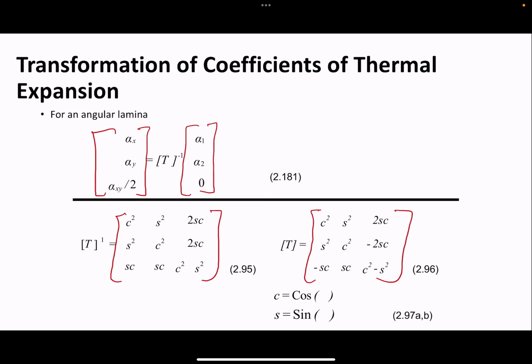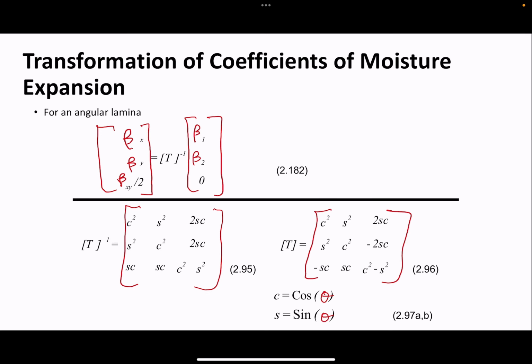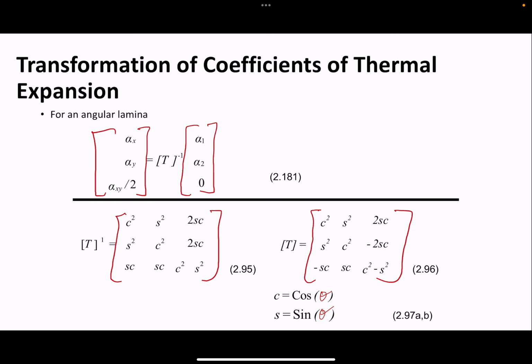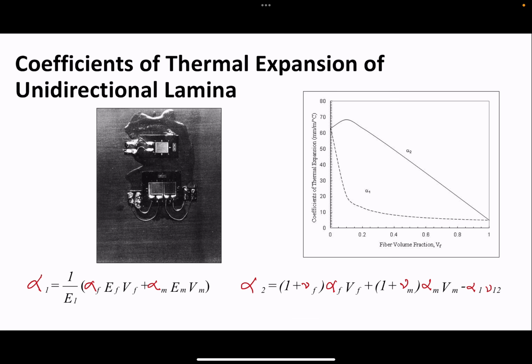So again, how to convert global to local, this you already know, is using the transformation matrix, which is a combination of sines and cosines. It's the same for alpha and beta. You can even see the divided by 2 that is there for the last value. If you have an angular lamina, because of the angle itself, it's no longer just x and y, you have xy, which is shear. But in the local direction, it's still 0, but you might have a value in the xy direction. So how do we experimentally get this?